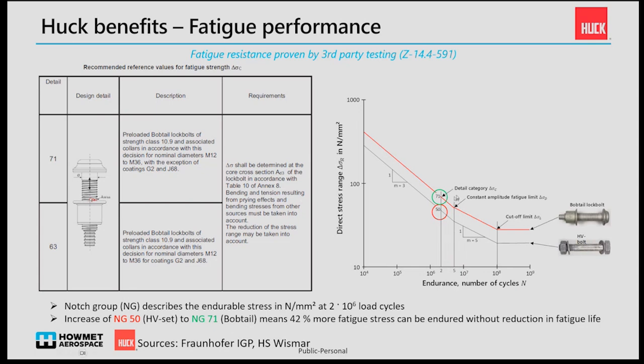Although the difference doesn't look very significant if you look at the plain numbers, it makes a bigger impression. For example, an increase from notch group 50 to notch group 71 means that 42% more fatigue stress can be endured per square millimeter for the same diameter basically. So this could result in using a smaller size of lockbolt or even using fewer fasteners in total if you switch from HV bolts or threaded fasteners to lockbolts.